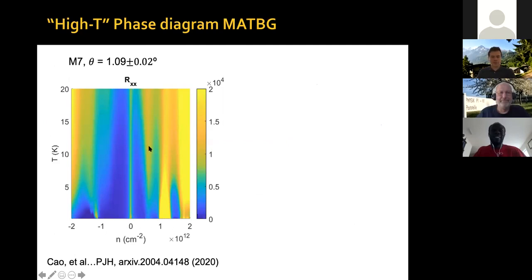As you can see, we have correlated insulating or semi-metallic states at 1, 2, and 3 electrons per moiré unit cell. For holes, something happens around -2. Okay, this is density. This is not filling factor. This is density of electrons. This corresponds to -2 holes per moiré, so 2 holes per moiré unit cell.